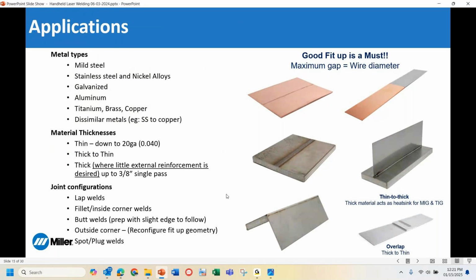So now getting into the fun stuff. As we look at the different applications that exist in the industry and where laser welding can be used, laser welding is pretty much able to be used on any material that can be welded with conventional fusion welding processes. The most common in the industry are going to be mild steel and stainless steel. We look at some nickel alloys like Inconel, potentially for the aerospace industry. Galvanized, it works very well with galvanized because it's such a low heat input process.